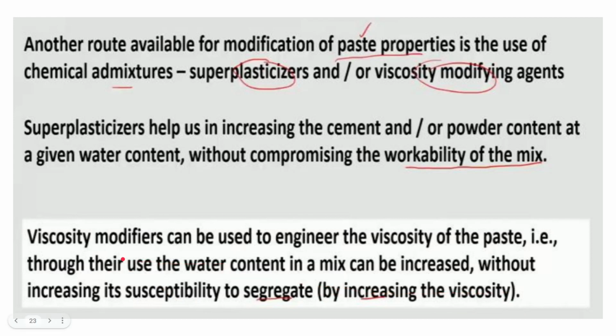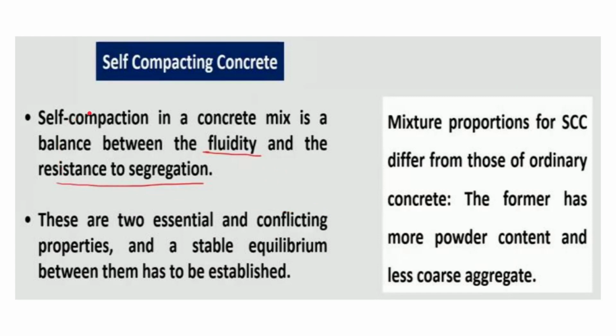So if we use viscosity modifiers, VMA, we can increase the water content, but we don't have to fear the segregation, because of the increase in fluid friction, which is definitely viscosity. Even if we increase the water content, we don't have to be afraid of segregation because of the viscosity agent. How they are useful, we will go through in the case of self compacting concrete.